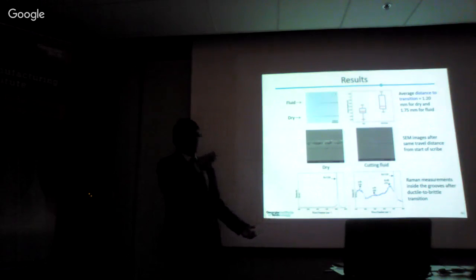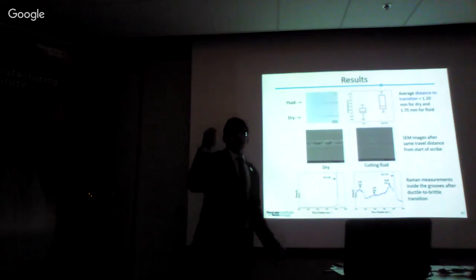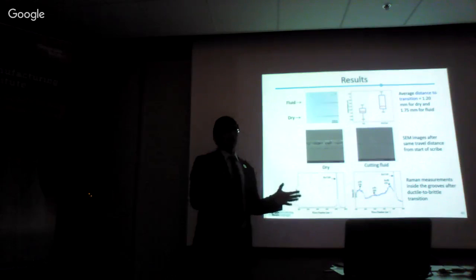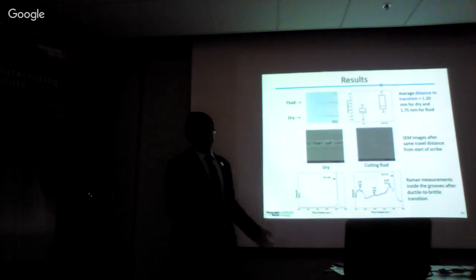If we analyze the Raman spectra of the silicon inside these grooves, for the dry conditions, we find again silicon of diamond cubic structure giving a 520 centimeter inverse peak, showing not much phase transformation is taking place. Compared to that, when the silicon is scribed using the cutting fluid, we see there is a lot more phase transformation, like amorphous silicon, silicon 3, which allows silicon to be removed in ductile phase.